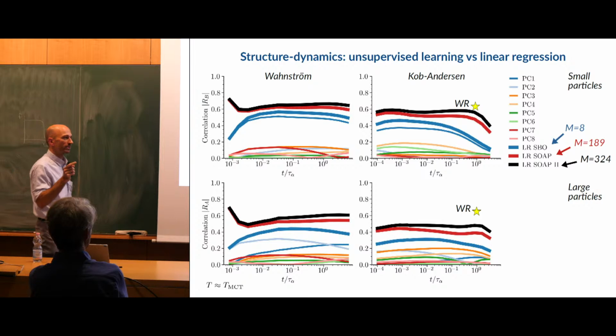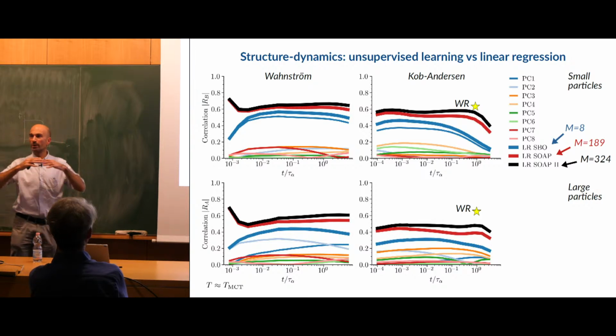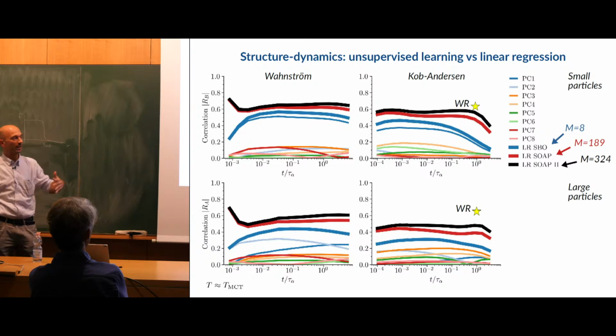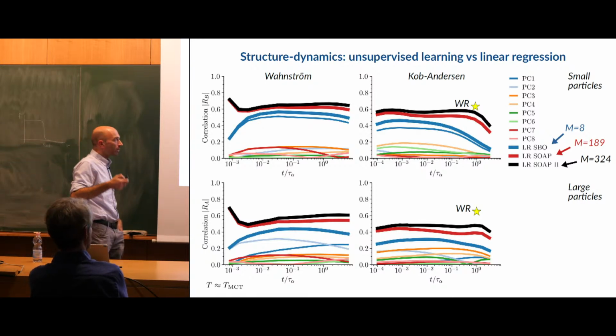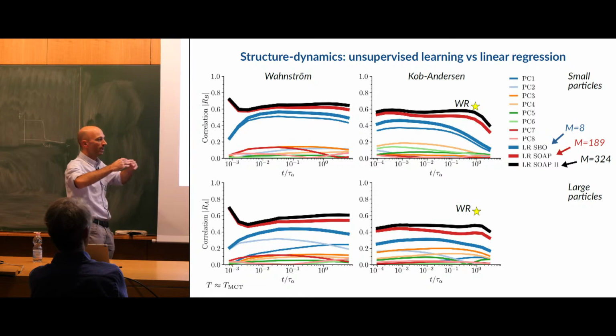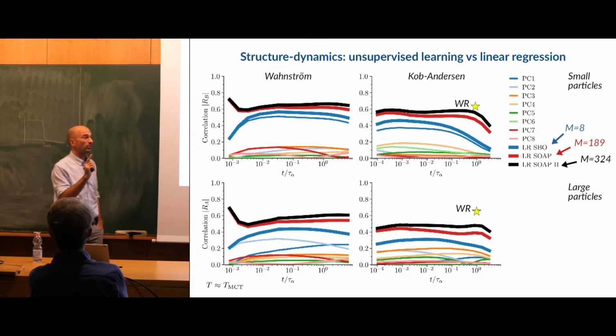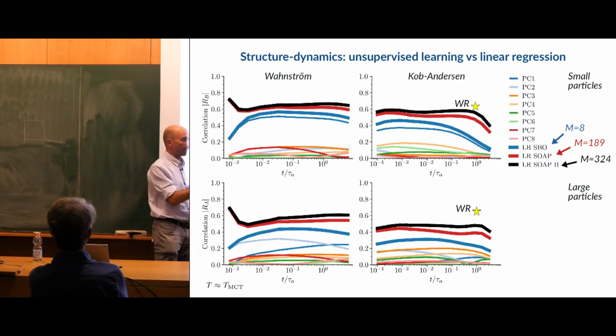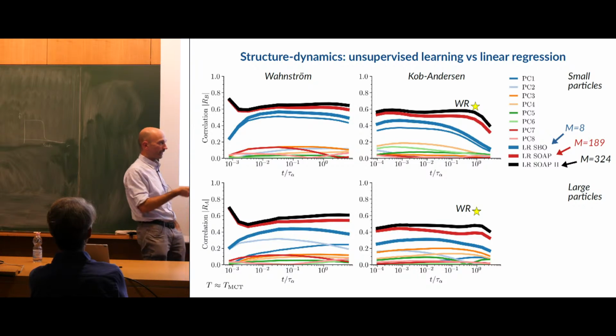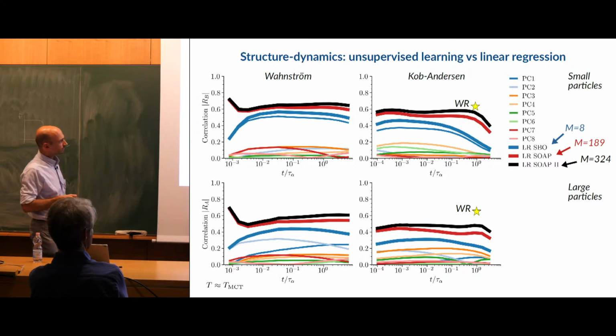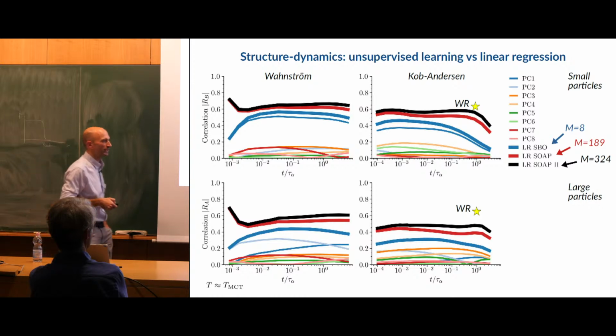So these two lines here are restricted to the first coordination shell. And we can go beyond. We can go up to the second coordination shell to see if it improves. And somehow consistent with what Laura has been telling us this morning, going to larger length scale allows you to improve slightly the correlation everywhere. Okay, so you get a better signal indeed up to the second shell. Keep in mind, these are correlation coefficients between individual particle propensities. I'm not doing any coarse graining, and I think there will be some talks about that later tomorrow. Probably with a bit more of coarse graining, we can get closer to the world record, which is here. We're not quite there.